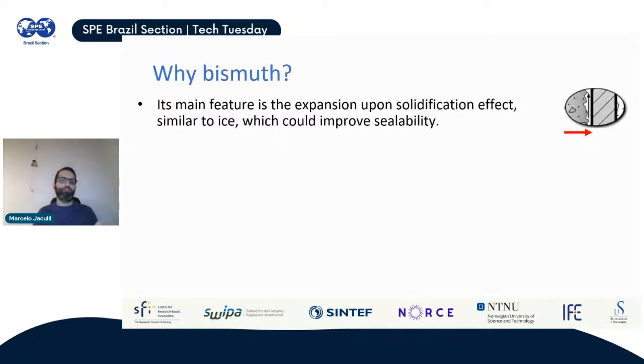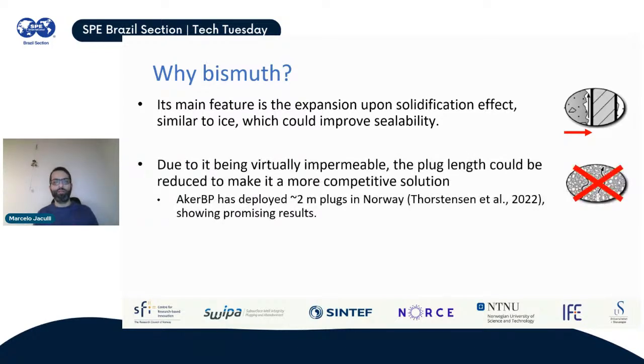Then why bismuth? Because of this main feature of expanding upon solidification, like what happens when water becomes ice. And the idea is that this can improve sealability. So if you remember from the picture, by having this alloy expand, you are reducing the gap between the plug and the pipe inner wall. And since it's impermeable, basically since it's a metal plug, you don't get any leakage through the plug, and then probably you can reduce the plug length.